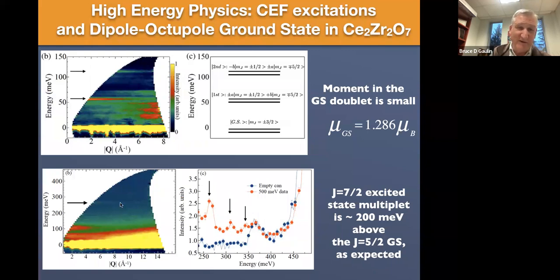These aren't terribly easy to see because they're at very high energies, but you can see them, and I've pointed out some of these features in these line scans to the right. But at any rate, this tells us that the J = 7/2 excited state multiplet is about 200 meV above the J = 5/2 ground state, as expected. And then we can do more moderately high energy spectroscopy that looks at the transitions from the crystal field ground state multiplet of the J = 5/2 cerium 3+ ion to its excited states. That multiplet has a degeneracy of 6, and it splits into 3 doublets, as you can see over here in the top right.